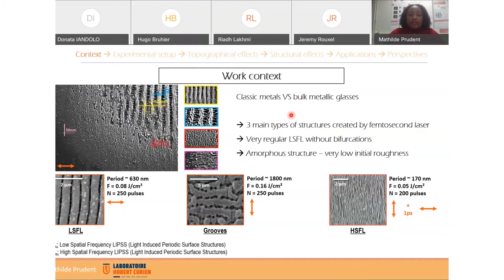And here you can see some types of structures that can be created after irradiation. For example, LSFL, so low spatial frequency LIPSS, and also HSFL here, high spatial frequency LIPSS. We can see that all of these structures present different orientation regarding the electric field direction. And also for classic metals, we have some irregularities and also a lot of bifurcation for these structures. It's not the case for the bulk metallic glasses. After irradiation with ultra-short lasers, we can obtain LSFL, regular LSFL with few bifurcations.